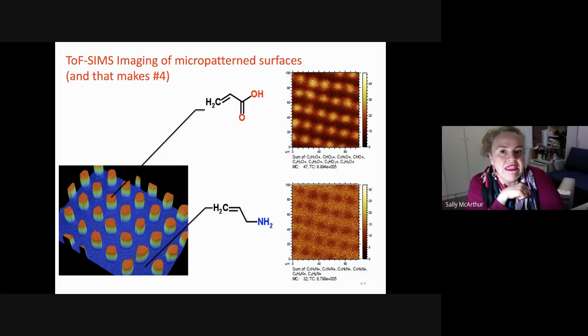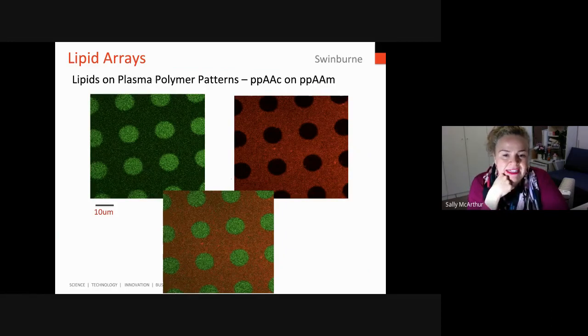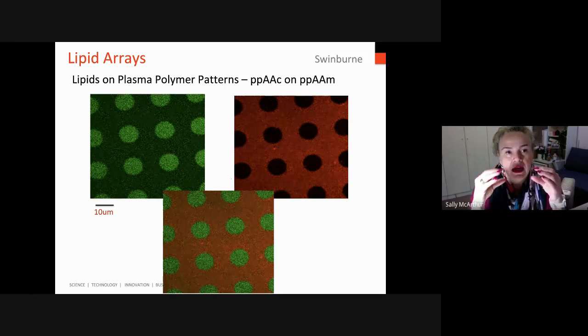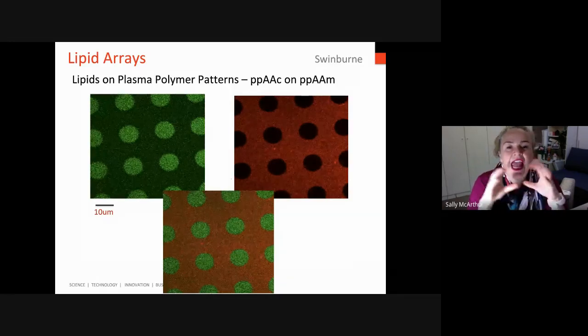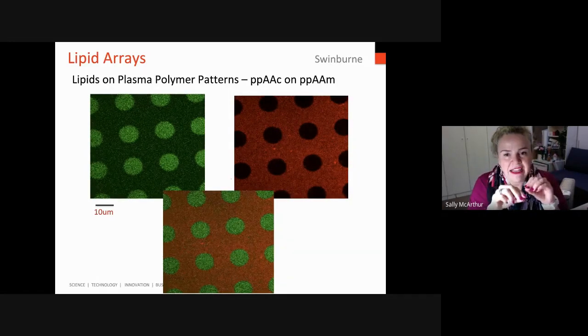And so what we did was then introduce our vesicles onto these arrays. And what you can see here is our lipids being patterned onto our acrylic acid and our allylamine system. But what we did was we took the same lipid and tagged it in one instance with a green label, and in the other instance with a red label. And so what this shows us is that we introduced the green labeled lipid onto the surface under the conditions that would enable it to attach to the acrylic acid.